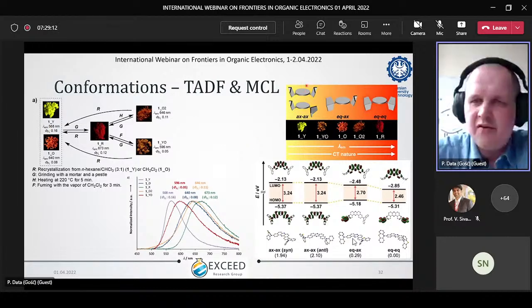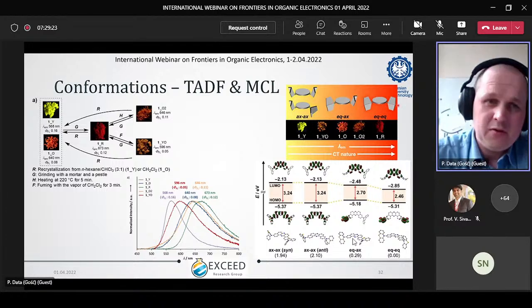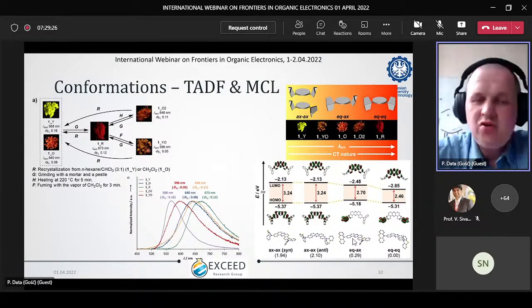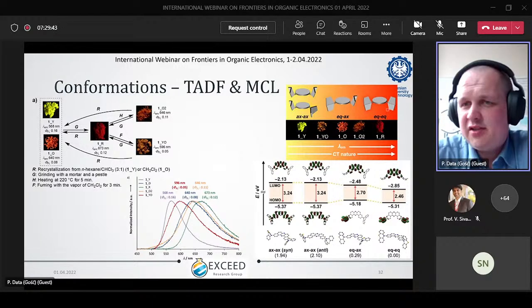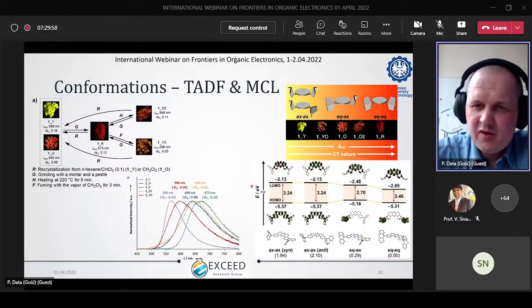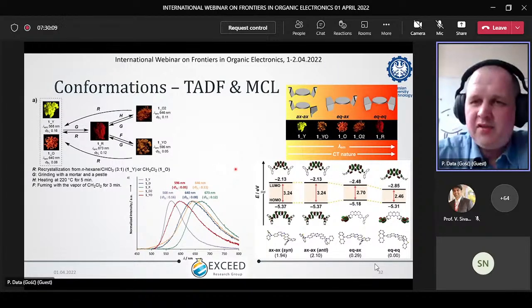So if you see the structure here, we have an acceptor and donors. And depending on the conformation, if it's axial, axial-equatorial or equatorial, we have different emission of the solid sample. With the equatorial, we are increasing our CT nature, decreasing our emission energy and increasing the wavelength. And we are increasing the CT nature and TADF properties of our molecule. You need to remember that in all those cases, it's the same compound, but it has a different molecular structure in different conformations, which affects our final emission and final efficiency.